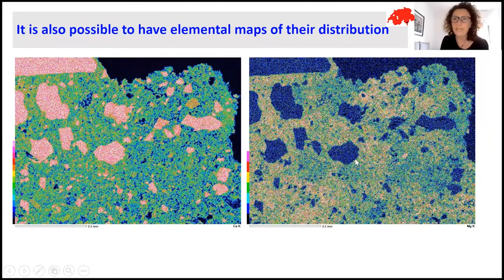So in this case, I can say that for producing this mortar, a magnesium lime binder was used, but the aggregate is mainly calcium carbonate.